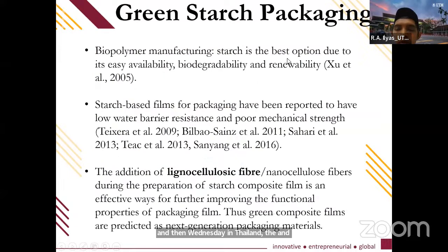How to overcome this problem? One of the methods is we change the synthetic or petroleum-based plastic to starch biopolymer due to its availability, biodegradability and renewability. The starch-based film for packaging has been reported to have low water barrier resistance. So although starch can be one of the solutions for the degradation of synthetic plastic, there are drawbacks with starch-based film. First is the low water barrier resistance, and the second is the poor mechanical strength.